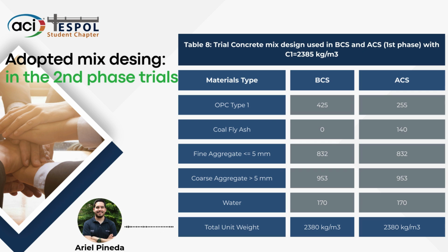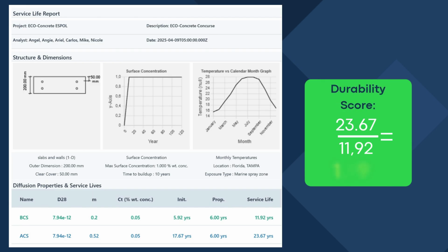The same amounts of water and aggregates were kept as in the base case. The only difference was the use of 60% cement and 40% fly ash as the cementing material. This mix achieved a useful life of 23.67 years, almost double that of the base case, which was 11.92 years. This is equivalent to a 1.99 times improvement in durability in marine conditions.